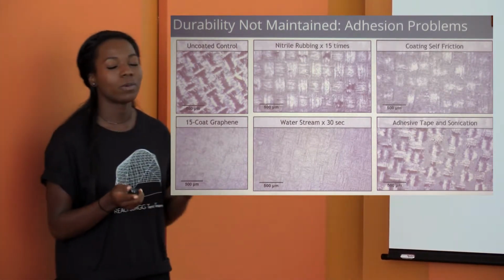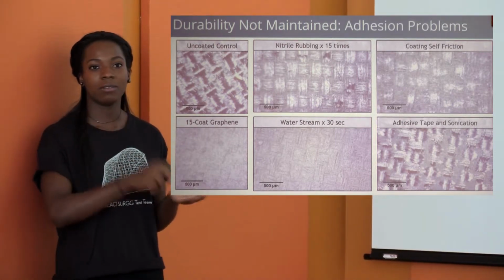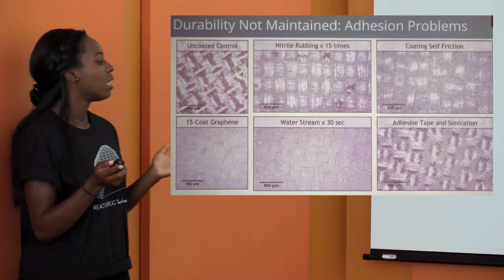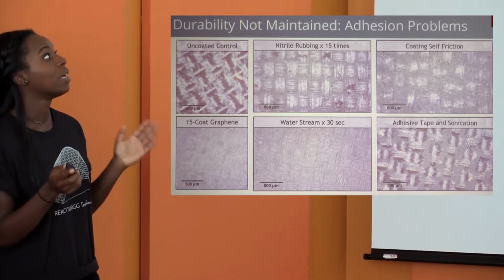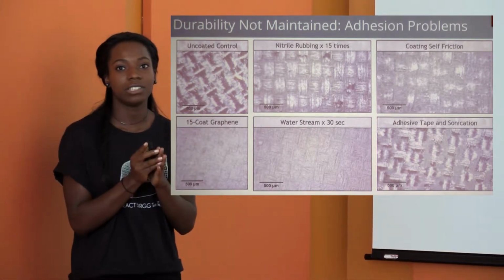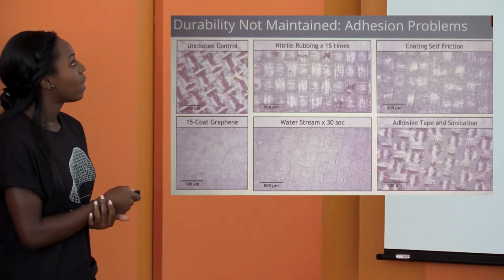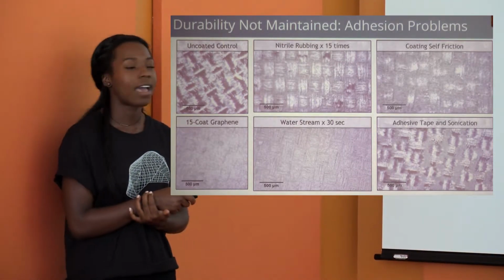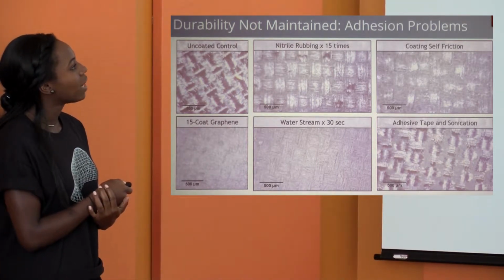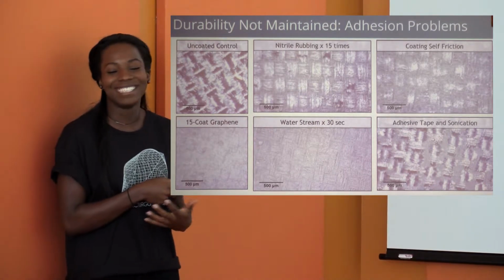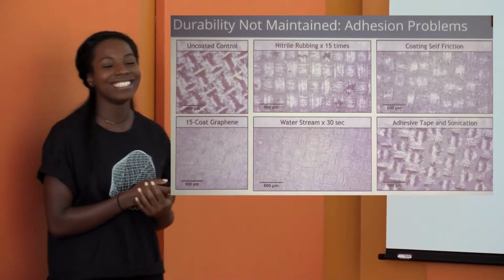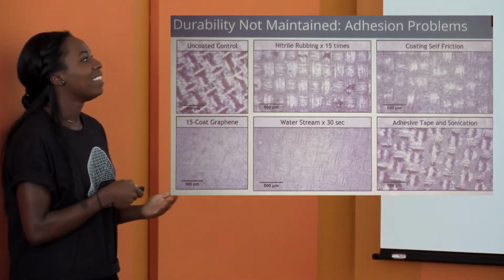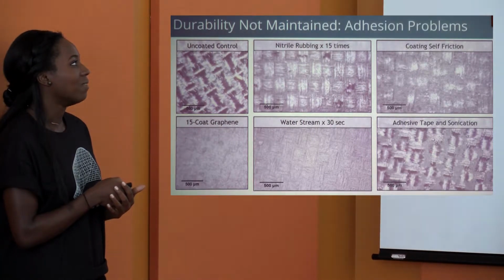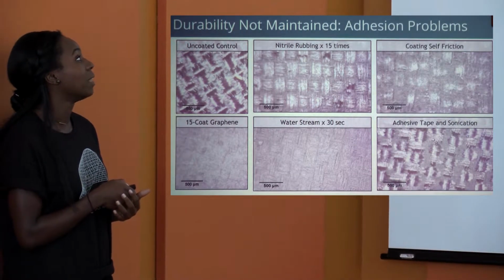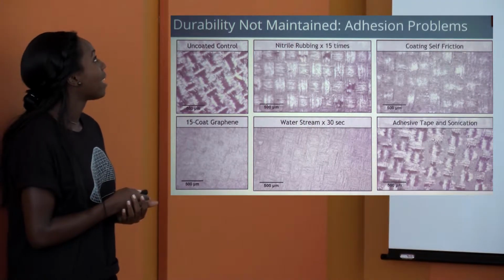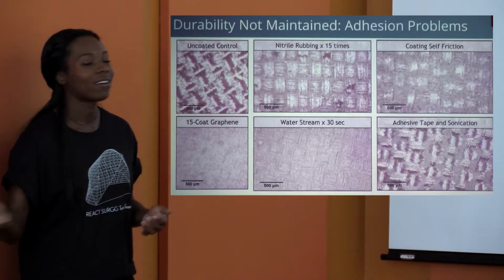We did a self-friction test, and the way our tent actually works is it collapses and opens up, so it's possible that when the tent is collapsed and opened, both sides of the coated layers will touch each other, causing some of the coating to come off. We also ran the coating under a water stream for 30 seconds, and you can see some of the coating was removed. And lastly, we really wanted to test, how durable is this coating. So we used adhesive tape and sonication, and you can see in this image that most of the fibers of the fabric end up being exposed in comparison to the other tests. And now I'm going to hand it back over to Griffin to see how we tackled that problem of adhesion.